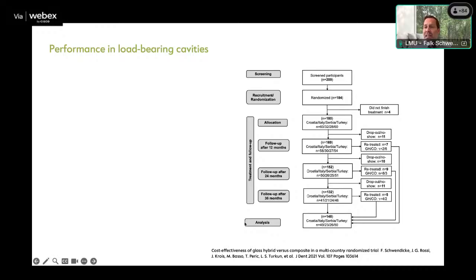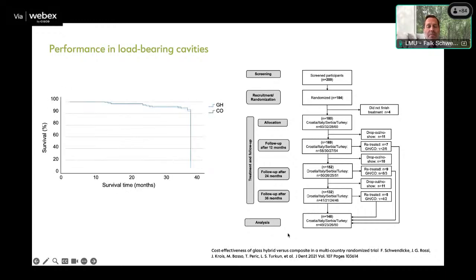And what was done in that study in a randomized fashion, the material was compared against a composite, where we could say, well, this is already an accepted amalgam alternative. And if we manage to have the glass ionomers faring roughly the same, then we are really at an important stage for the whole discussion of making the case for glass for amalgam replacements. And this is the survival curve we have yielded in that study, where we compare the failure of glass hybrids versus the composites.